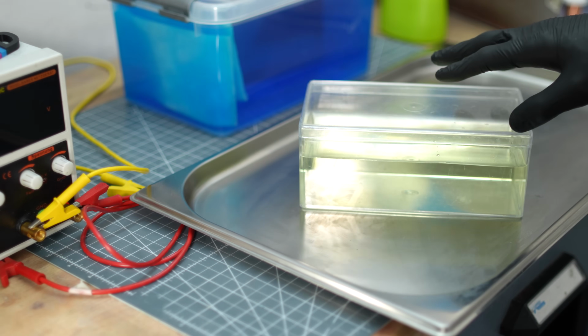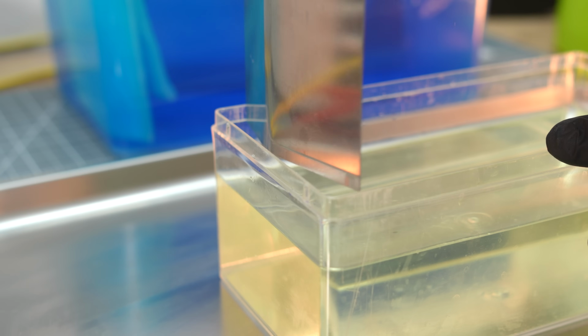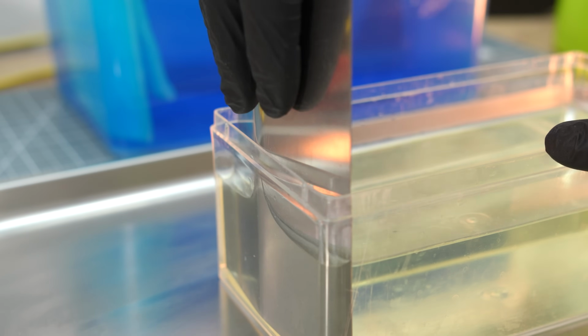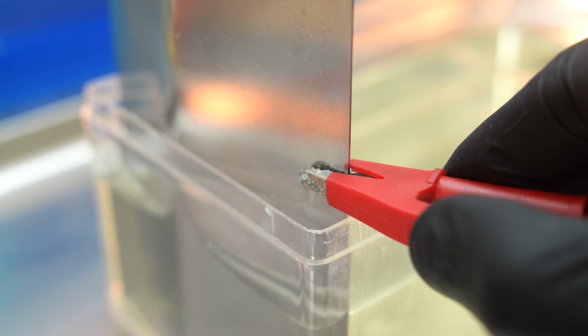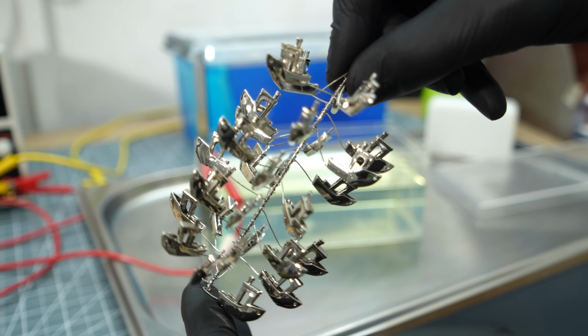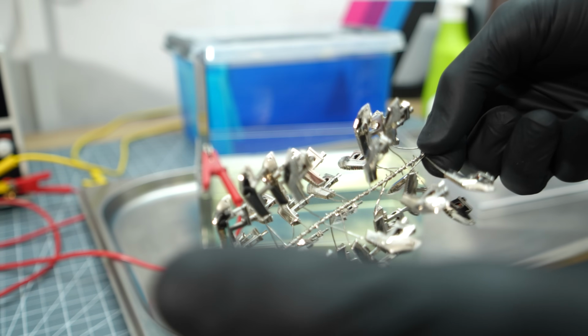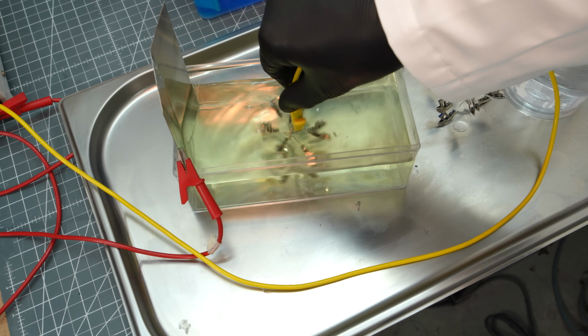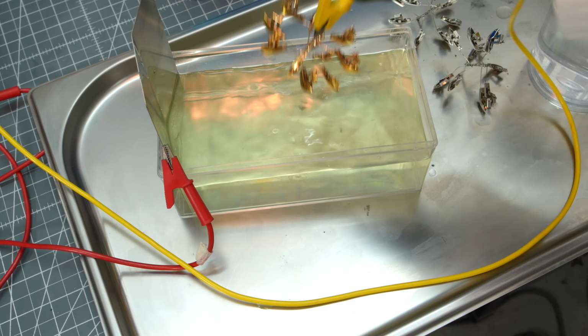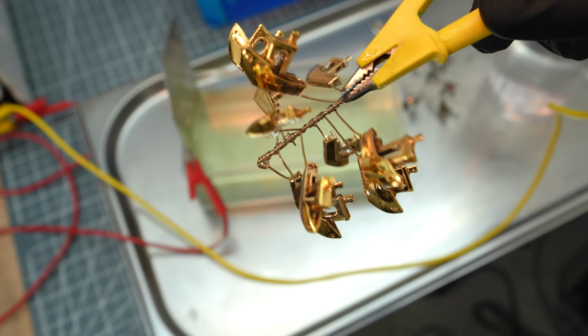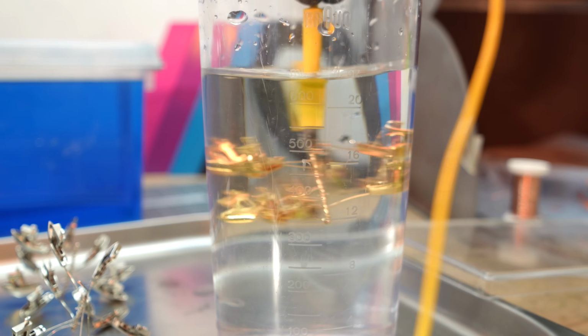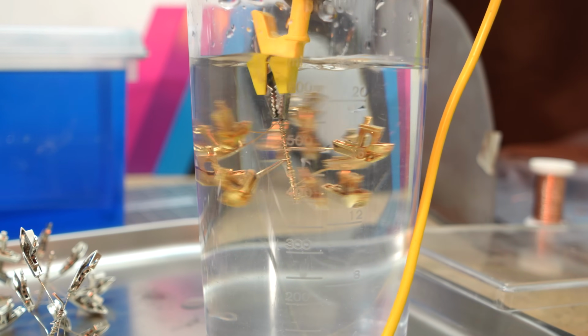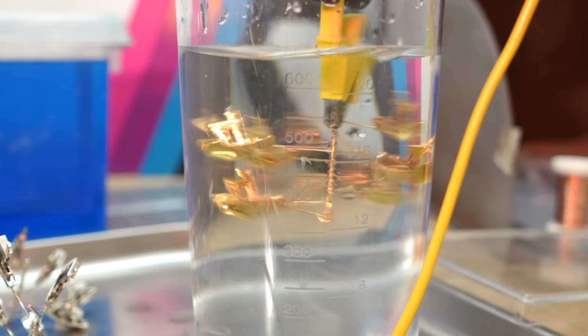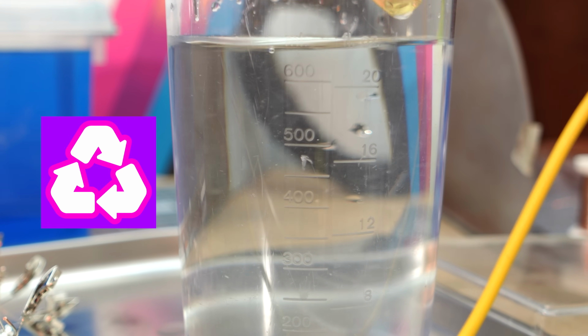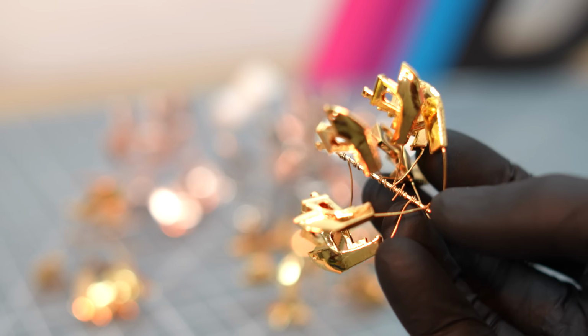Caution is advised with gold electrolytes. It must not come into contact with acid, as it can break down the cyanide complex, resulting in the release of highly toxic fumes. Therefore, I always rinse with plenty of fresh water between the electrolytes. Like nickel, gold electrolyte deposits very quickly, and the longer I leave it in, the more golden the surface becomes. Now I rinse the print again in fresh water. Honestly, I collect all electrolyte residues in separate containers and take them to the recycling center. It's the right thing to do. Look at this gold.